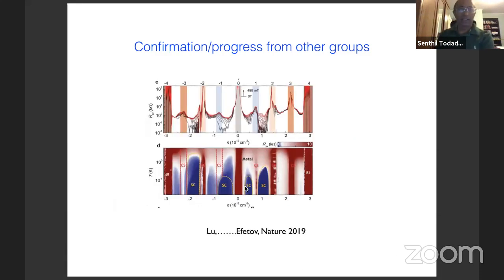And the field evolved quite a bit more, was pushed forward by this third paper that came from the group of Dima Efetov. So he made twisted bilayer graphene devices and then had some way of controlling a type of inhomogeneity that people knew existed in some form or the other in these devices, which is an inhomogeneity in the twist angle, where it varies slightly from one location to the other location. So Efetov's group thought they had a way of controlling that a little bit, and then they found an even broader range of dopings in which the system is superconducting. And these superconducting regions are punctuated by regions of correlated insulator. Right? So you see these resistance peaks that correspond to the correlated insulator and flanked by superconductors in a wide range of doping.